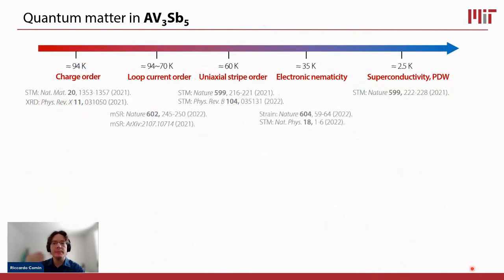And so the phenomenology of these Kagome metals is remarkably rich. You have this charge density wave or charge order transition at 94 Kelvin, but then you have this loop current order happening at a lower temperature, uniaxial stripe order, electronic nematicity, so breaking of rotational symmetry, and then at the lowest temperatures you have superconductivity. And all of these things happen in the very same material.